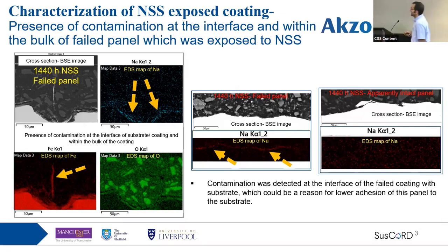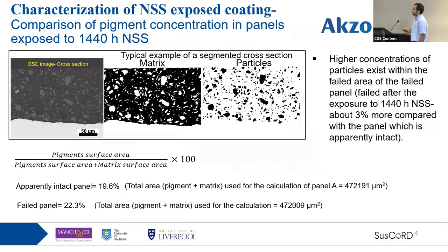and here I compared it with the samples which didn't show any signs of failure, and as you can see there are no contaminations at that interface. So I think this contamination has resulted in lower adhesion of this coating to the substrate, but I believe it's not the main reason for the failure, and I will try to convince you later in the next few slides. So the next thing that I started to do is some image analysis.